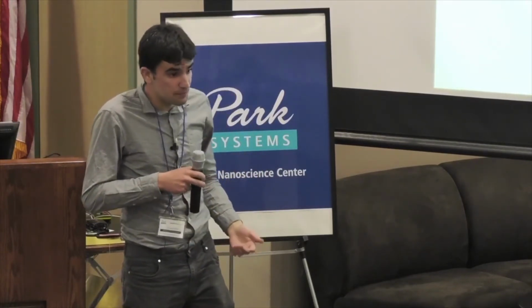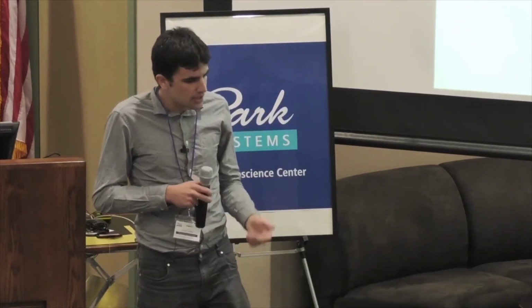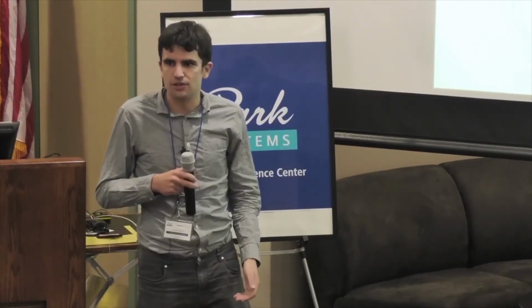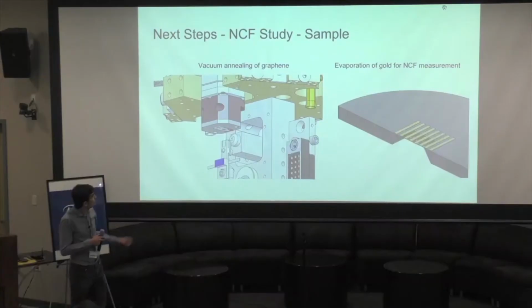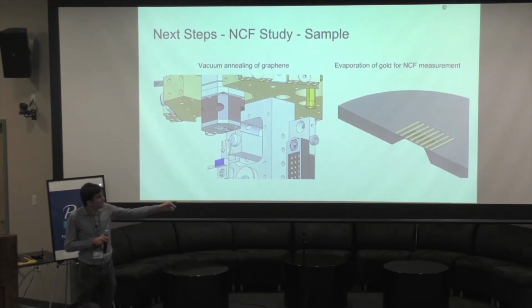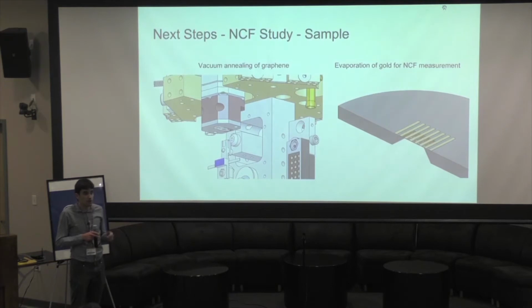The other thing that we've been working on is preparing sample processing and sample concepts for a larger non-contact friction study. It's been found in the literature that annealing under vacuum can reduce the impurities in graphene and potentially reduce the non-contact friction. So we've built a heated sample stage to enable in situ thermal annealing of the graphene. And then we also are considering evaporating gold strips onto these graphene on silicon nitride membranes to provide another relevant material against which non-contact friction can be measured in the same experiments.